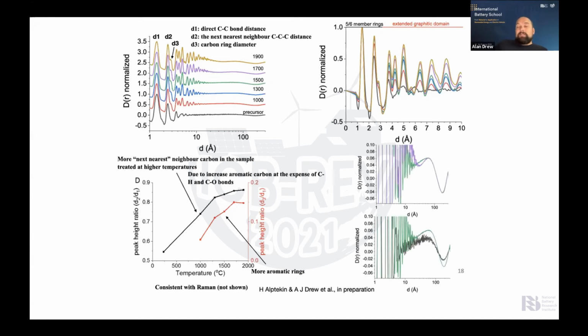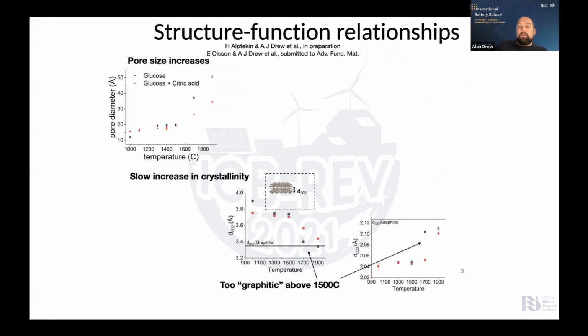Then if you look at the higher Q stuff, where you're looking at nanopores, you can see there's also something going on here. Okay, so this is between black and green. You can see here that it becomes sharper. And then between green and purple, it becomes sharper still. But the actual position of the pore size distribution doesn't really change very much. It's just the sharpness that changes. Okay, that does suggest that it's the order that changes rather than the actual structure, but nonetheless.